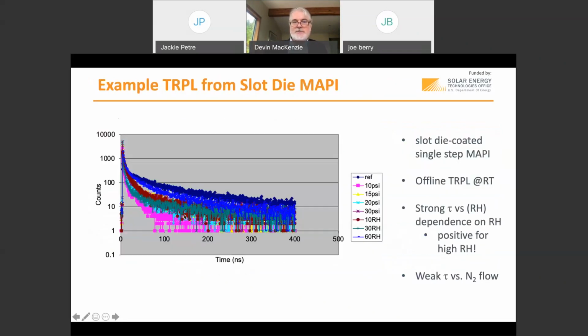And this is just an example. This is offline time-resolved photoluminescence signals off of a slot-die coated film and a spin-coated reference film. There are interesting trends here. There's a strong tau in the lifetime versus relative humidity, but it's characteristic that we see this dip in the middle, and actually at high humidities we see long lifetimes. I think that's been observed by other people as well.